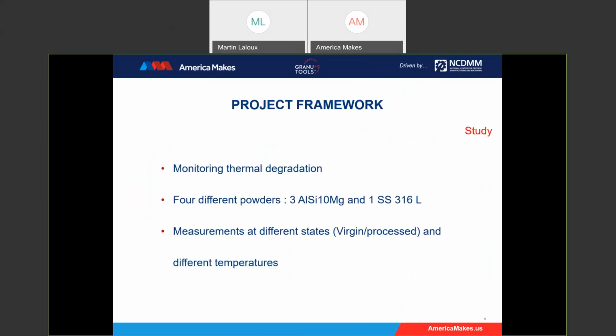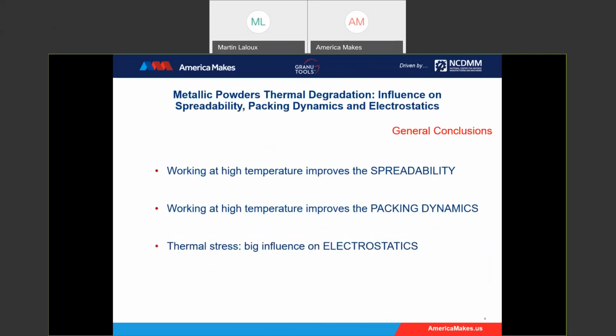For the project framework in this study, we wanted to monitor thermal degradation with 4 different powders: 3 different aluminum alloys and 1 stainless steel powder. We measured those powders at different states. First virgin powder, and then processed powder at different temperatures. If some people are in a hurry, they have the whole picture here, but then I will show you how we arrive at those conclusions. Working at high temperatures improves spreadability and packing dynamics, and thermal stress can have a big influence on the electrostatic.